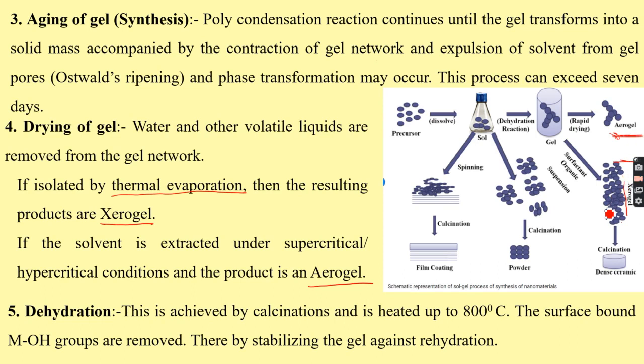The aerogel or xerogel is then subjected to a dehydration process, achieved by calcination with heating up to 800°C. The surface-bound M-OH groups are removed, thereby stabilizing the gel against rehydration.